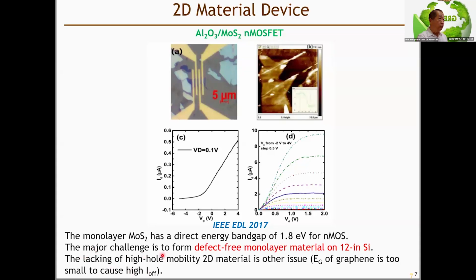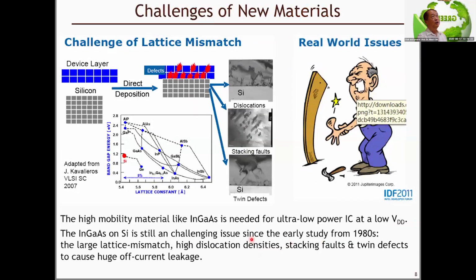However, the major challenge is to form the defect-free monolayer material on a 12-inch silicon wafer. The equipment right now is for 12-inch wafer manufacture, so we must use the same wafer size to manufacture the single layer two-dimensional material. Another issue is that there is no high hole mobility 2D material for P-type hole conductive PMOS. So that's a challenge. The challenge for materials like a 2D material is very difficult.